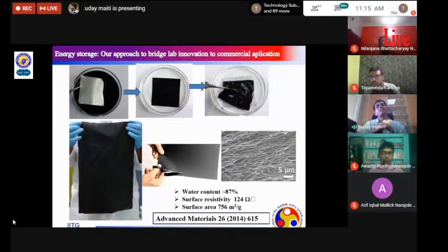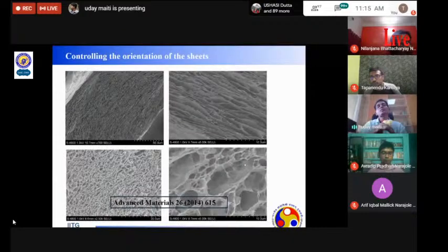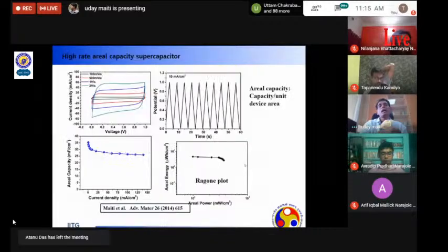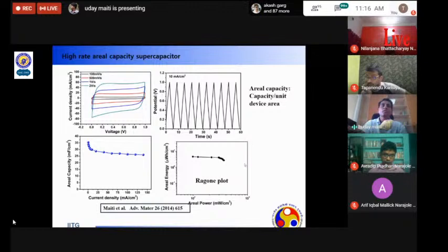By this strategy, we can actually reduce their restacking, and we can of course control the orientation of the sheets by tuning the dilution conditions. And then we used it for supercapacitive energy storage, and we have found that it can be charged and discharged at a very fast rate. Within some millisecond scale, you can charge it.